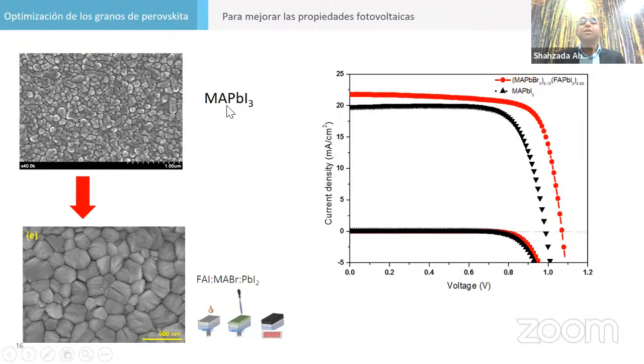Because methylammonium lead iodide absorbs till 780 nm, and this is a band gap of 1.54 electron volt. But if you take formamidinium, it absorbs till 820 or 800. So if we can shift the absorption onset to a higher wavelength, we can absorb more light. If we can absorb more light, we can generate more current. Similarly, if you replace some iodide with bromide, the band gap will increase. If the band gap increases, we will have a higher VOC. So by playing with all these things, people came up with different types of strategies.